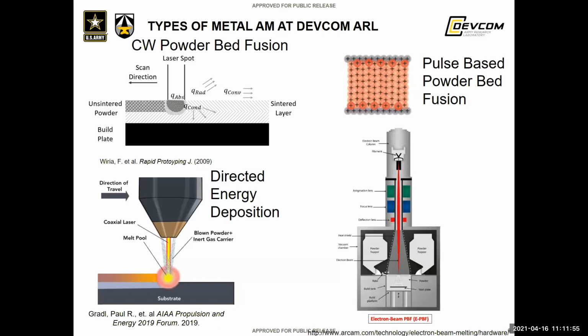So there's an extra layer of first order processing parameters that you have to worry about. Instead of just worrying about the speed, the power, and the hatch spacing, which is the spacing between single layer scan lines, you now have to worry about the speed being split into two parameters, which is the dwell time, the length of time that the laser is on for, as well as the distance between these pulses. So it creates basically a different type of defect set that we now have to deal with.